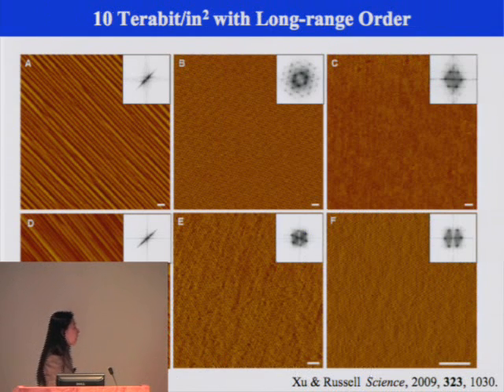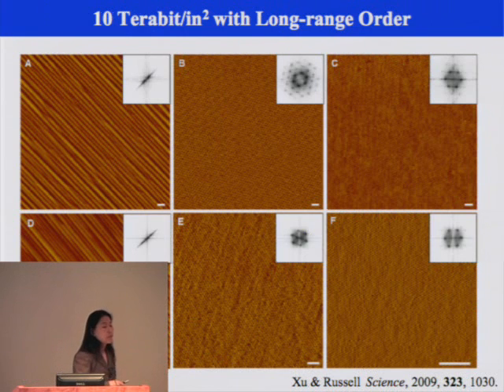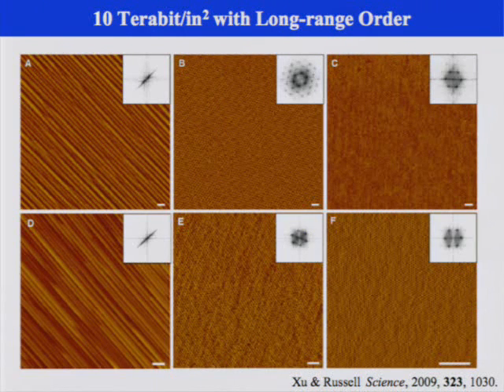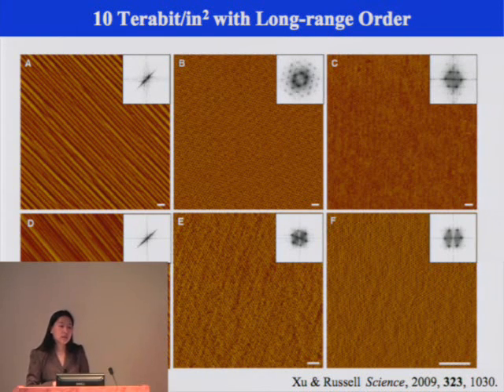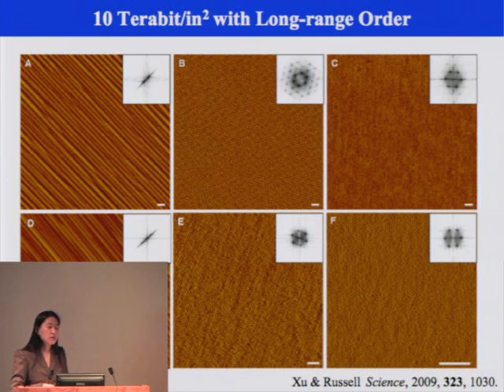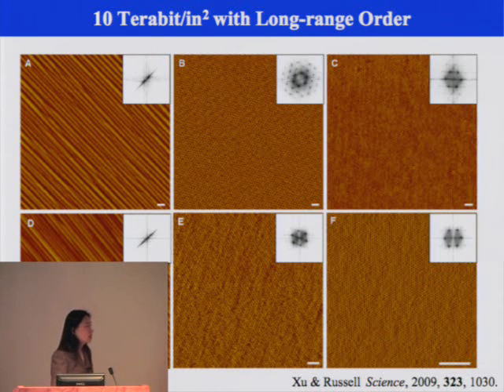So these are a series of AFM images, and this is one sapphire substrate with a certain frequency, with a certain periodicity. And then those are two different polymers with different molecular weight. You can see in this case I can easily tailor the spacing as well as the feature size just by changing the molecular weight I have. And again, I can also take another substrate and then you have different spacing in there.